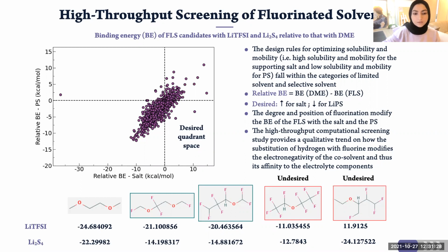We also found that the degree of fluorination and the position of the fluorine atoms, where they replace the hydrogen atoms in the conventional glyme, can affect all of these properties, including the binding energy. And this kind of high throughput computational screening provides a qualitative trend on how the substitution of a hydrogen atom with a fluorine atom modifies the electronegativity of the co-solvent in lithium-sulfur electrolyte, and therefore its affinity towards the electrolyte components.